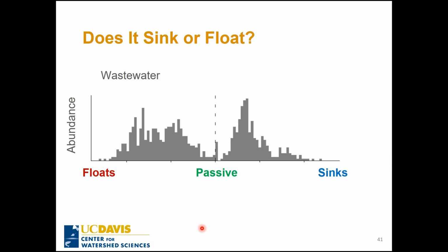In particular, I wanted to point to two features here. One is this peak on the slightly sinking side. These are primarily polyester fibers. And you can compare that to a section of the buoyant side, polypropylene fibers. As I'll show in two slides, the difference between slightly sinking and slightly buoyant is huge in terms of fate. But you could really only distinguish these particles if you did have that spectroscopy to actually understand what is the plastic polymer of each particular particle.